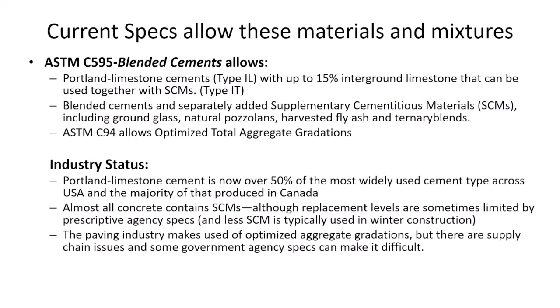For example, C595, the blended cement spec, that's where the type 1L cements ended up. There's also a type 1T, which is limestone plus an SCM, such as fly ash or slag. So it allows you to blend these materials. And as I said, C94 allows optimized aggregate gradations.